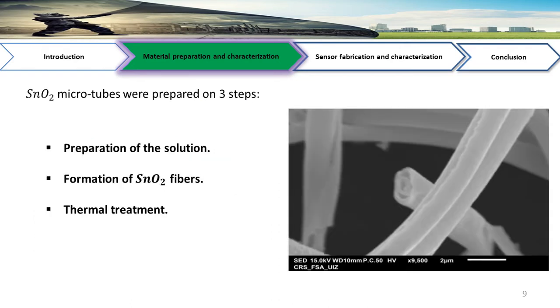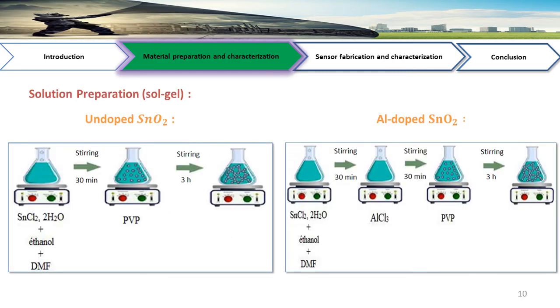The tin oxide microtubes were prepared in three steps: preparation of solution, formation of tin oxide fibers, and thermal treatment. The solution was prepared by dissolving tin chloride dihydrate in a mixture of DMF and ethanol under magnetic stirring for 30 minutes. Subsequently, PVP was added, followed by stirring for 3 hours at room temperature.